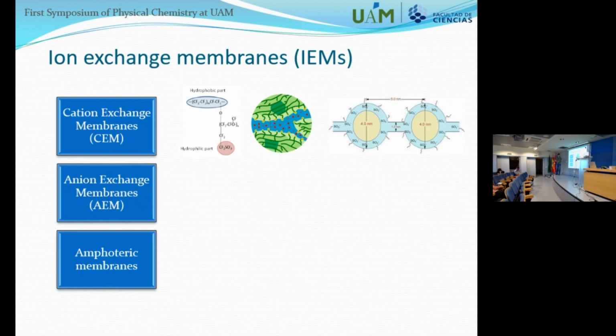So most of the effort is trying to find membranes that may have similar or even better performance than the Nafion membranes, but with lower cost. And also one of the things here is that the cation exchange membranes, since they help to conduct positive ions, for example, if we are working with the vanadium redox flow battery, as we saw before, the reactive species are positive ions. And we don't want to help conduction of that through the membrane. We want the active species to stay in their chambers. So one of the drawbacks that the cation exchange membranes have is that they usually have a higher crossover of the vanadium ions than other types of membranes.